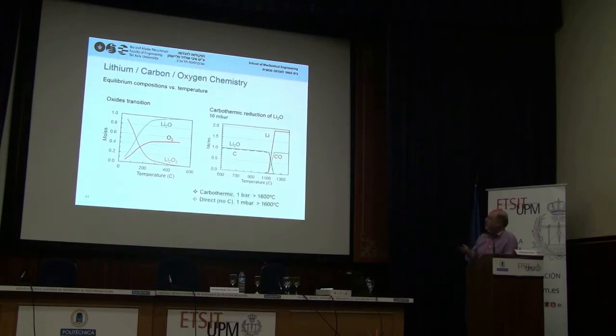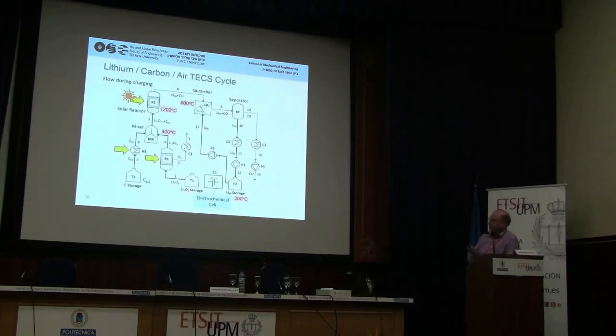Now this needs to be done at a slight under pressure or slight vacuum. And if we try to do it without vacuum, the needed temperature is again ultra high temperature of 1600 degrees. If we try to do it without carbon, again, we need these very high temperatures. So it seems that a more practical or reasonable thing is to have this combination of adding carbon and doing this at a slight vacuum. And here's the cycle that we should have.